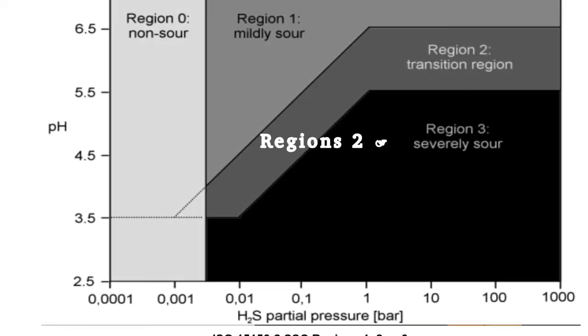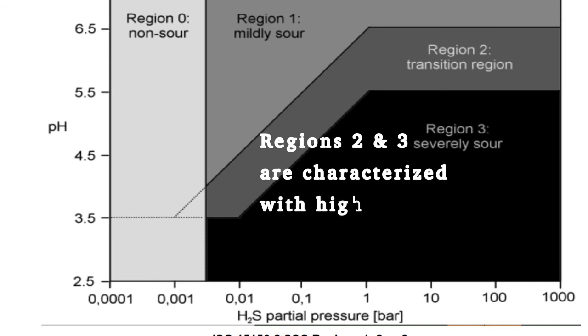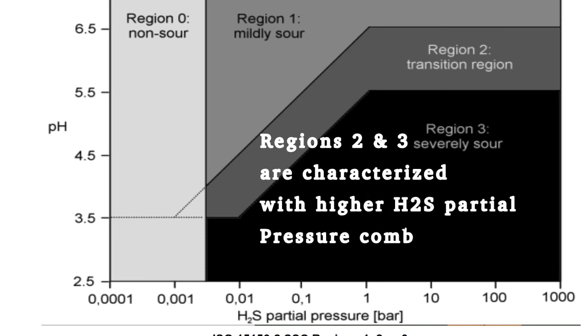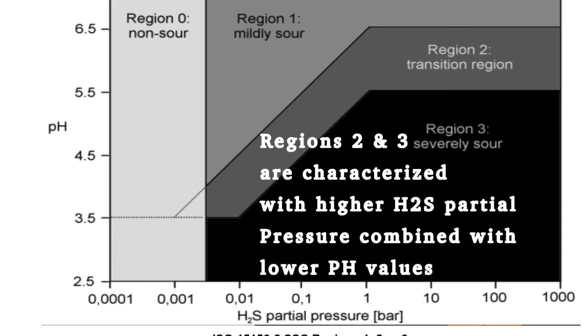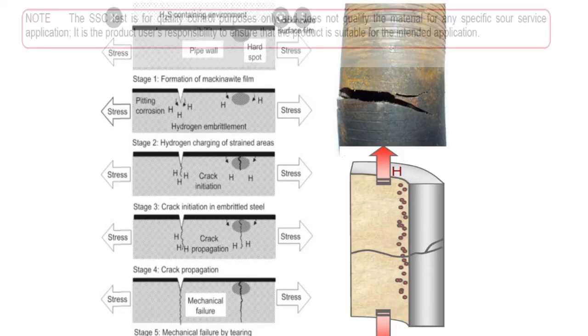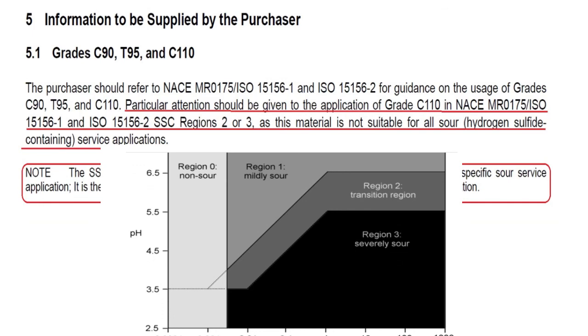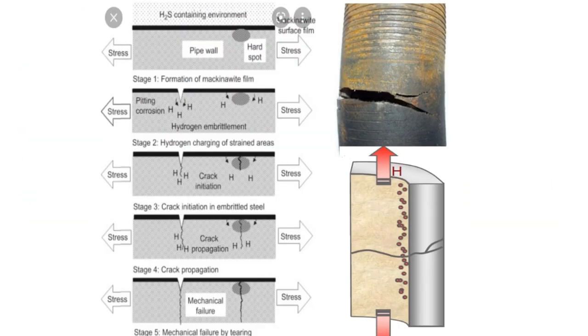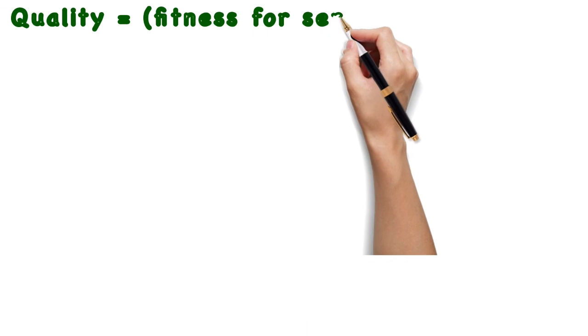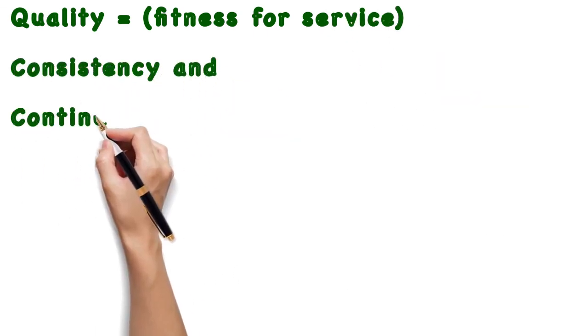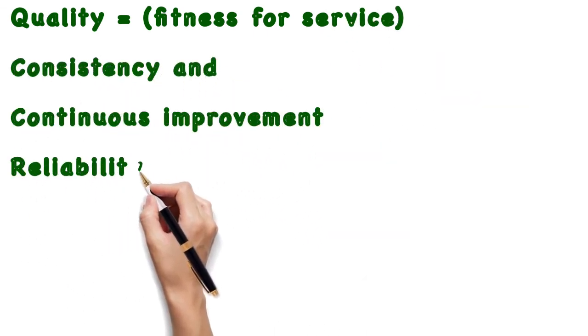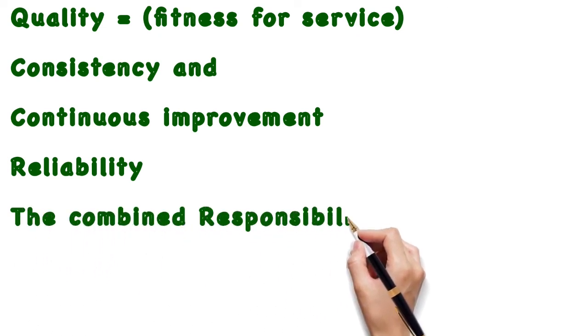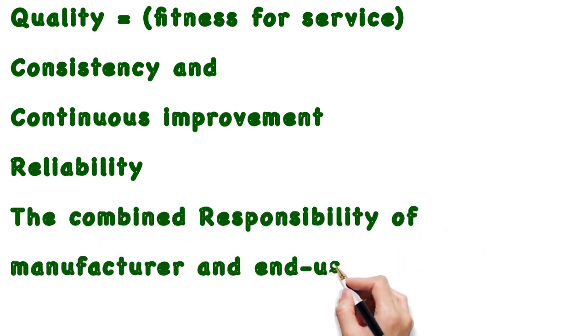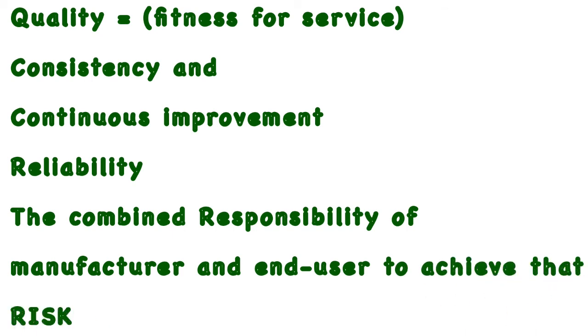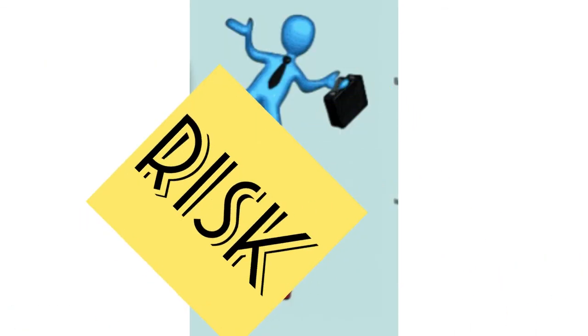So, regions 2 and 3 are characterized by higher H2S partial pressure combined with lower pH values, higher acidity. As you can see, this example summarizes almost everything that we have learned about the definition of quality as fitness for service, consistency, and the importance of continuous improvement to achieve reliability, and the combined responsibility of manufacturer and end user to achieve that, especially when we deal with risks. And this is what we will learn in this part, which has just started.